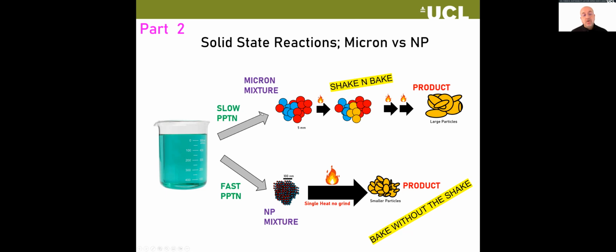So in the top part, you're generally mixing things together. So this could be a precipitate, or it could just be a solid state reaction where you take two oxides and you try and mix them together, and then you're doing shake and bake. Or it could be a precipitate where the elements are segregating because it's slow precipitation. So you may have an area that's nickel rich or cobalt rich because the precipitation was slow, and they have different rates of hydrolysis. And what happens is the orange area is the product.